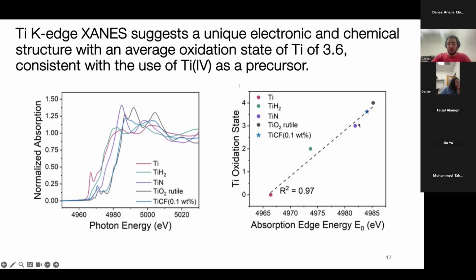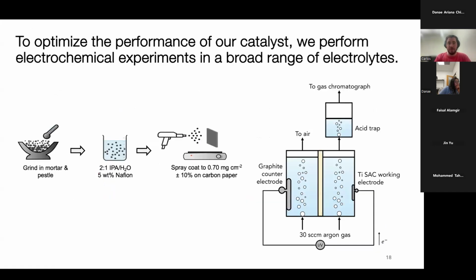And we can plot the absorption edge energy versus the oxidation state to get an idea of where our catalyst would be. Based on this, we estimate that our catalyst has an oxidation state of about 3.6. This mostly follows the idea that we have for the structure of the catalyst being ligated to 4 nitrogens. It is not perfectly 4 because the number can be brought down if you have some nanoparticles in the titanium state that have an oxidation state of 0, but it is close enough to 4 that it is consistent with our use of Ti4+ as a precursor.